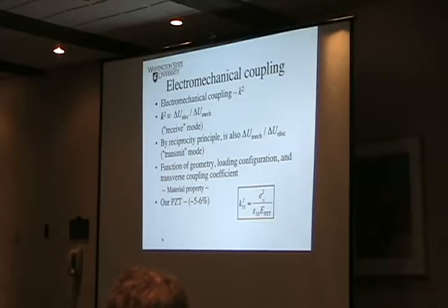So we had our k-squareds, and they're still not what we'd like them to be. We'd still like them to be much, much higher, and so we started looking at this a little bit more carefully. And for the PZT we use, the best we're going to get on something like a k-squared is about 5 to 6%. And that's really based on a couple things.